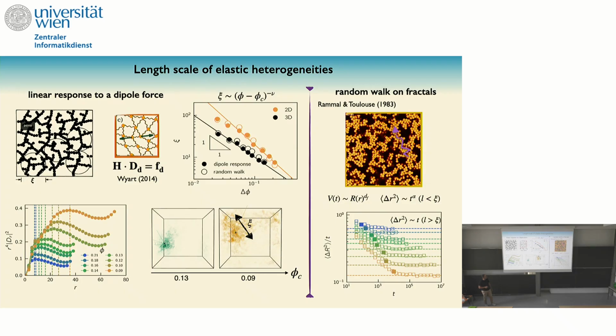Imagine that you have a picture of your system, and experimentally you can find the position of your particles. Then what you can do is put a tracer particle on the backbone of your network and tell it to do a random walk. Very simple. Computationally it is not very heavy. You just need to know the position. You put it, it does a random walk. If you have a system that is homogeneous and you have a random walker on it, then it will diffuse right away. It's a diffusive particle. But if you have something that is heterogeneous, you would expect a deviation from diffusive behavior. The particle needs to really explore many configurations. It will be subdiffusive, and then at some point it starts to diffuse.